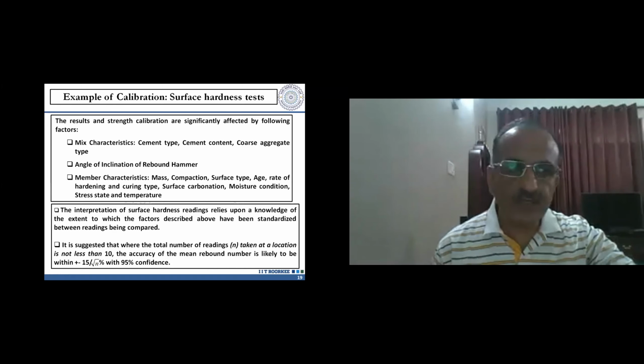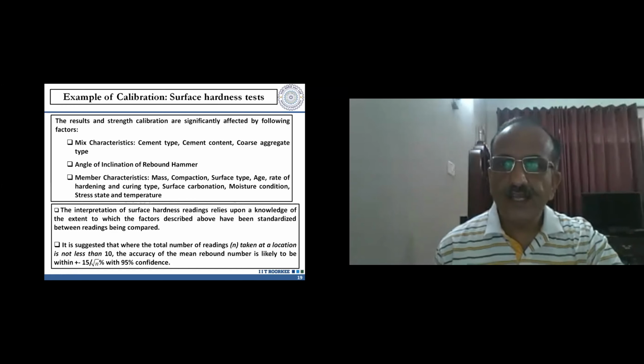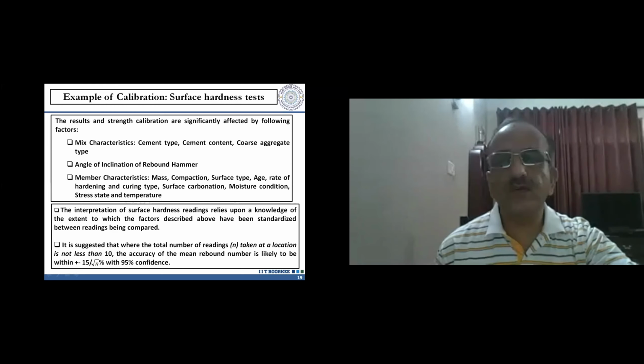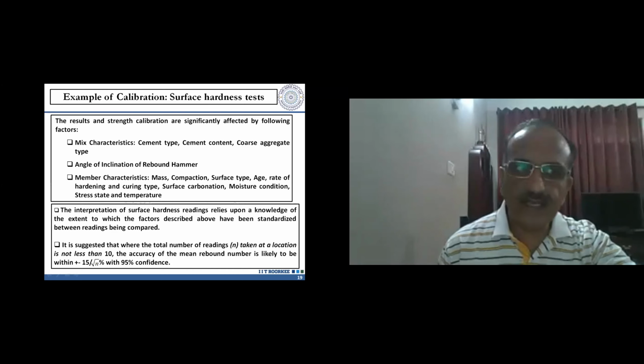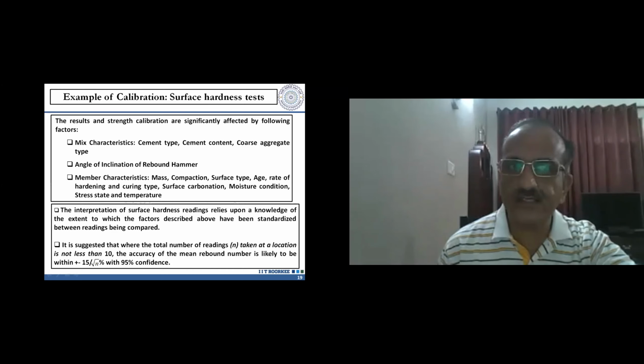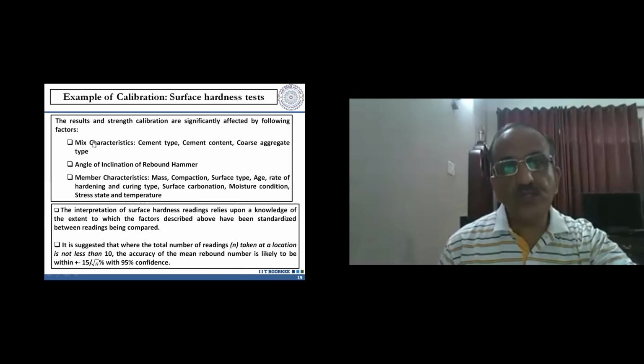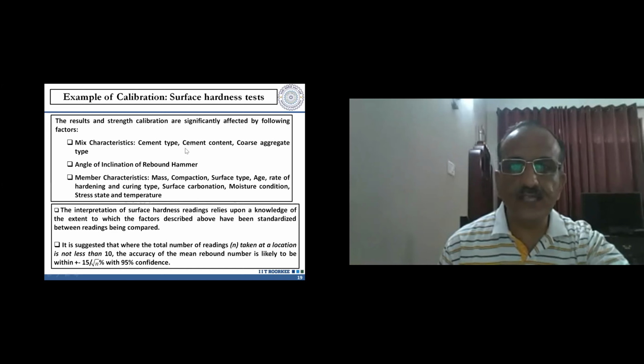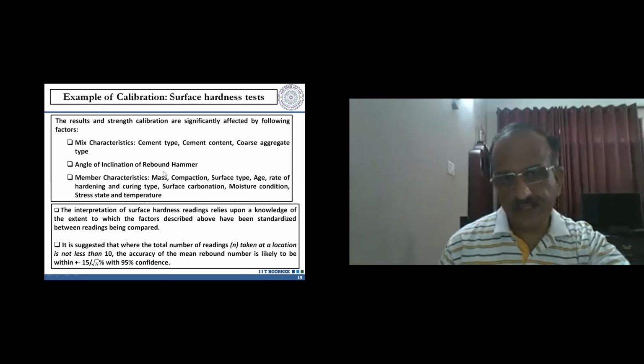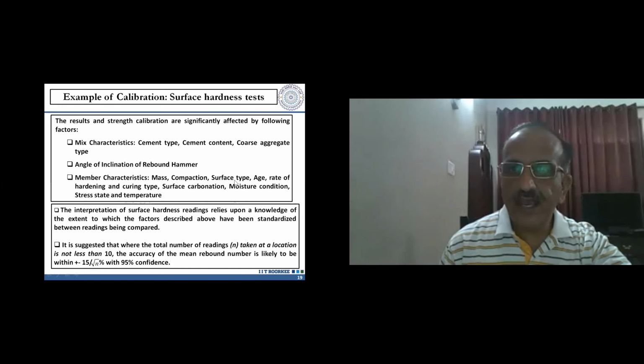Only when you use a site specific chart and you apply some corrections can you say that your reliability of estimating the concrete strength is good. Otherwise it is not. Otherwise, as I said, if you are just reading the standard chart and finding out concrete strength, it is not correct. If you have to do that, then apply these corrections, because that chart is for different concrete. Understand your concrete and understand their concrete based on which the standard chart was prepared, and then apply these corrections. Aggregate has a huge influence to play. Cement content, cement type, angle of inclination, of course, that we always apply. Member characteristics, mass, compaction, surface type, age, rate of hardening, curing type.